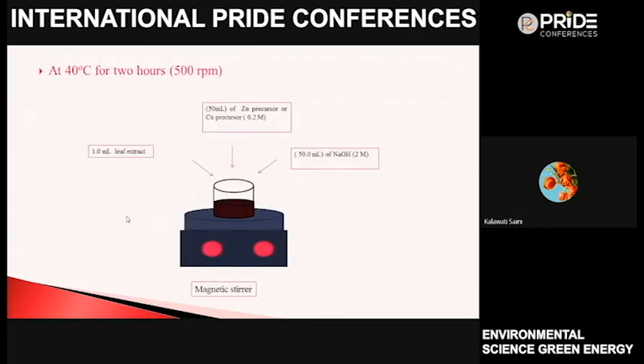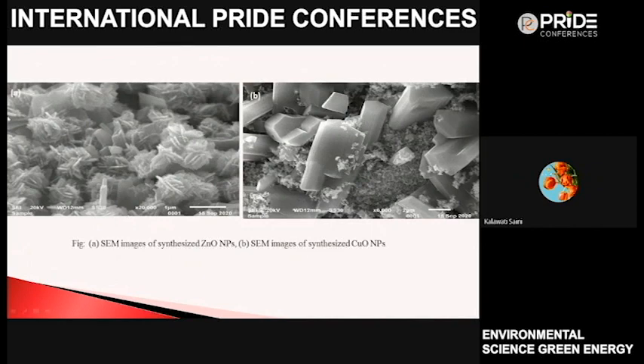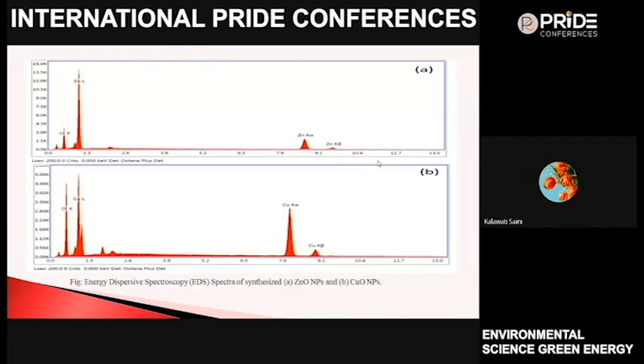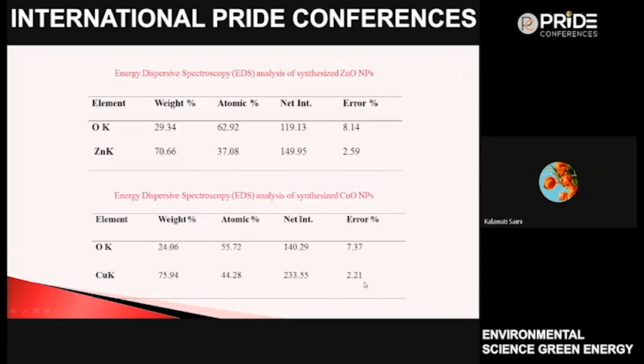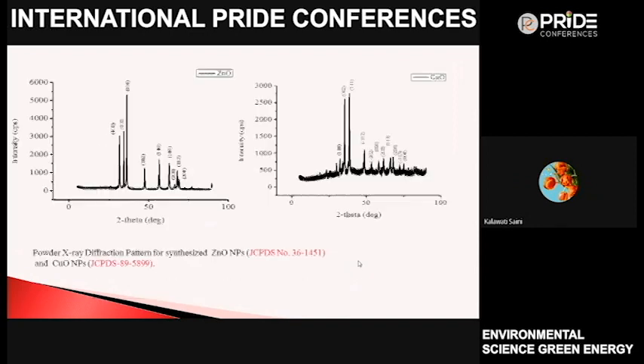This is the schematic diagram. These are the FESEM images: the zinc oxide nanoparticle is flower shaped, and the copper oxide is bigger sheet shaped, as well as a few smaller size particles are obtained. These are the EDAX results. This one is regarding zinc oxide, and the next one is for copper oxide. These are the atomic percent ratios which we have obtained by EDS.